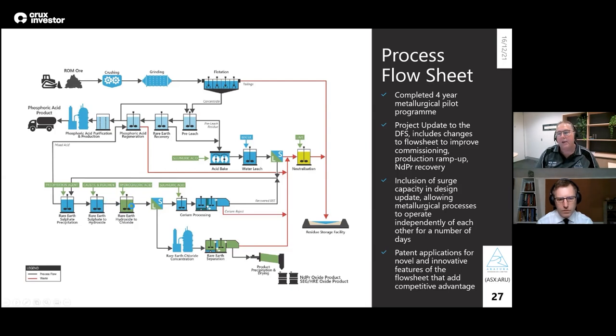And that means we don't have to carry all of that cerium, which is by far the biggest mass of rare earths, into the solvent extraction circuit. We do purify the cerium, but mainly to recover any lost NdPr from it, because the cerium's not worth a lot. And with NdPr production growing worldwide, there's a good chance that price is not going up anytime soon. We can produce it later if we want to.